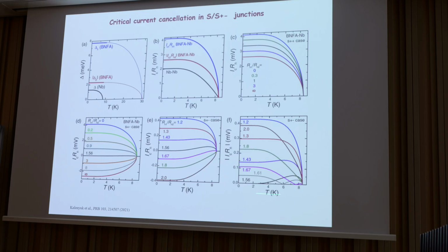And if you look carefully in this area, one can expect a very peculiar temperature dependence with a cusp. So it's actually going from positive to negative. In experiment, of course, you would always measure positive, which would show this cusp in the temperature dependence. And this is entirely due to a slight variation of the shapes of the temperature dependencies at different depths, with different amplitudes.